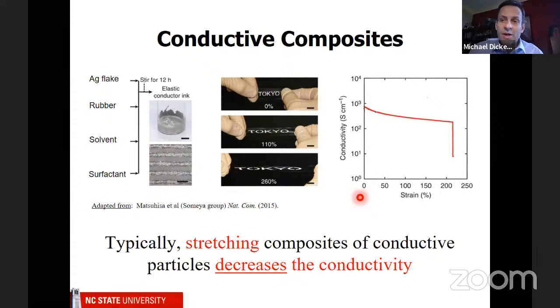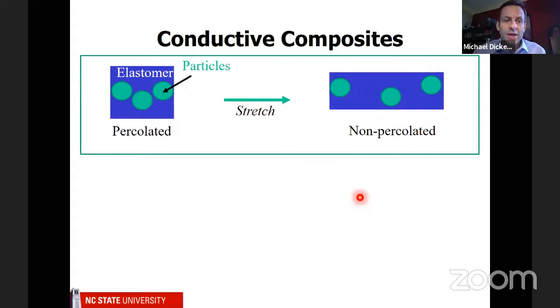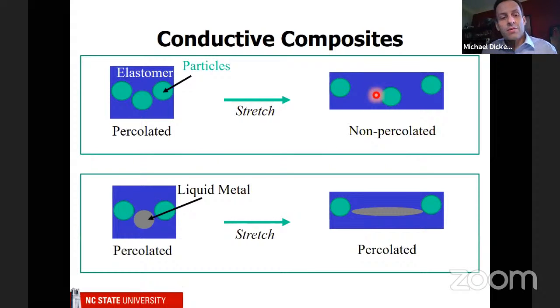And so that's kind of a problem if you want to have a stretchable circuit. The reason that's the case is that if you have particles, again, this might be silver, and you stretch them, you pull them further apart. So it's more difficult for the electricity to go through the material. In our case, because we have solid particles and liquid particles, when you stretch them, you actually can stretch the liquid metal particle, and you can maintain percolation, which just means there's a path for electrons.